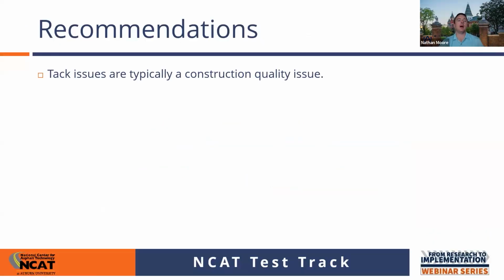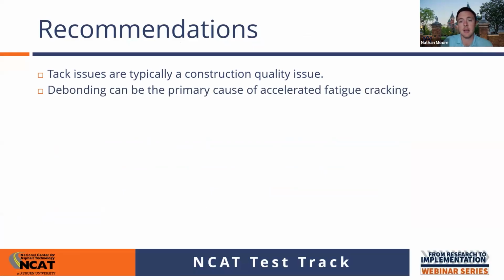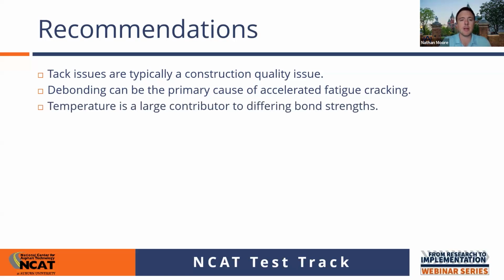Very good. So, Randy and Sean both pointed out tack issues are most commonly a construction quality issue. There may be materials related, but construction quality is key. Randy, I thought your slides about the accelerated fatigue cracking, both middle up and middle down, were really insightful. And debonding can be a cause of accelerated fatigue cracking. So what's on the surface may be affected simply because you have slippage between layers.